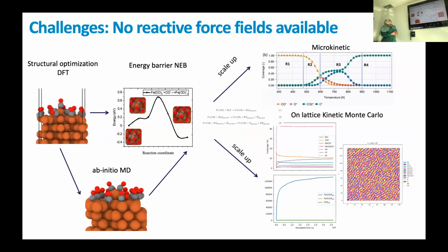So what I showed you is that if you have enough computer power, you can do structural optimization using DFT. You can calculate the energy values using, for example, the nudged elastic band (NEB) method in VASP or others. If you have the chance as well, I will show you when you are sometimes forced to, you can use some ab initio MD. And then the main purpose here, if you want to go multi-scale, is to use some other methods. One of them is kinetic Monte Carlo, if you have a good potential. If not, you could use microkinetics and also on-lattice kinetic Monte Carlo. Okay.